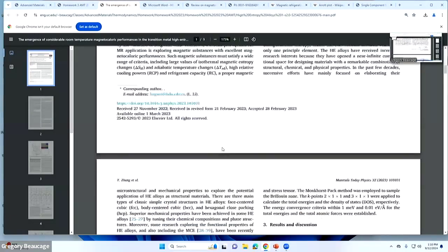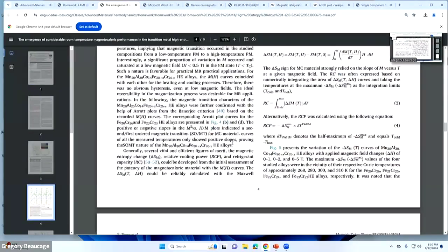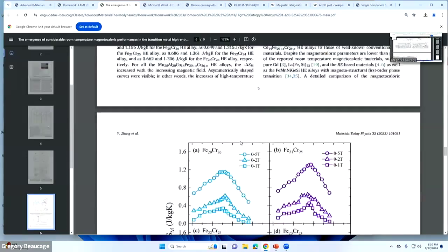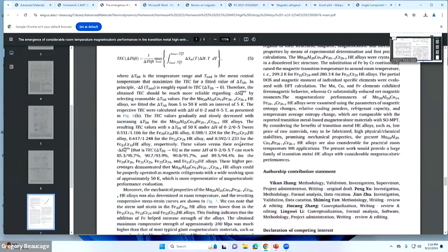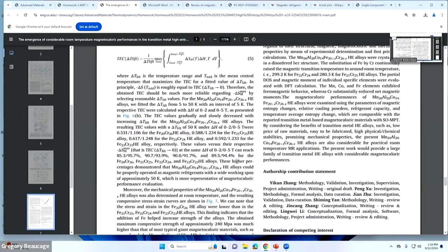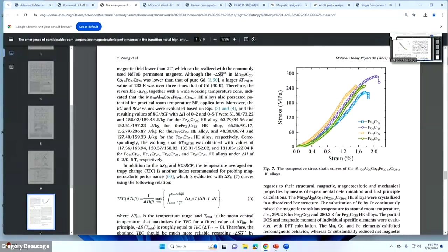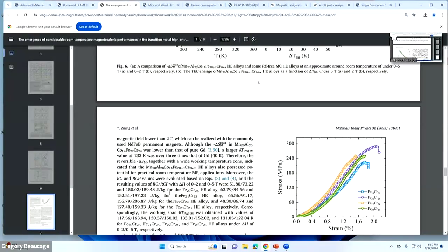Okay. So if you go down and scroll through this and get to the actual numbers they're getting out of it, somewhere here it gives joules per kilogram of this material that they can get out of this transition. Here, it's about 150 joules per kilogram, right? I asked you to look up something like melting water, or ice.